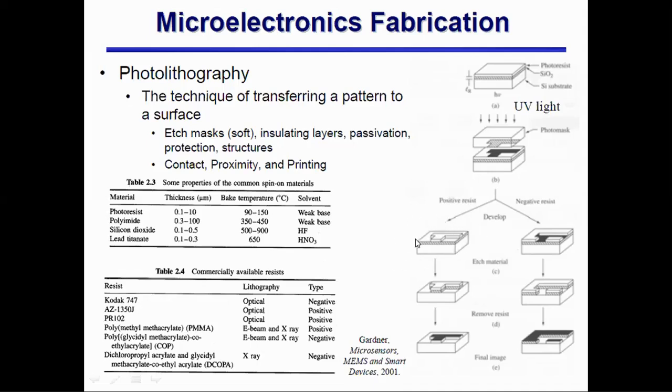So if you are using positive photoresist and then you put in the developer solution, next we have to put the wafer in the developer solution. We have to develop the photoresist. The process is known as development of photoresist. We have to remove some portion of the photoresist. Here, if it is a positive photoresist, the portion which is exposed, it would be etched out in the developer solution. Developer solution would eat that portion which is exposed to UV light.